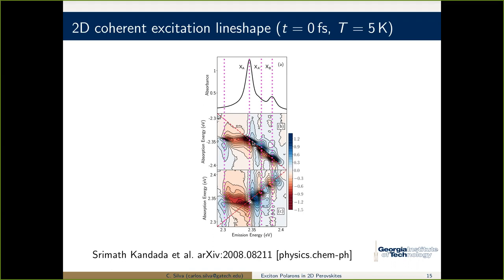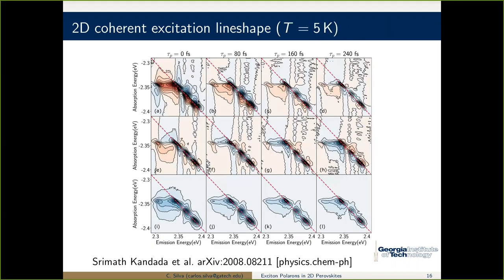But we now go in time, and here it started dispersive, the real part. But after 240 femtoseconds, it looks absorptive now. Here's a main peak centered around the diagonal. And if I look at the imaginary part, it looked like an absorptive component, a peak centered on the diagonal, but eventually it's dispersive. So these are the many-body correlations, the exciton-exciton many-body correlations that give rise to what we call excitation-induced dephasing. It's this dephasing process that I described in the earlier slides.